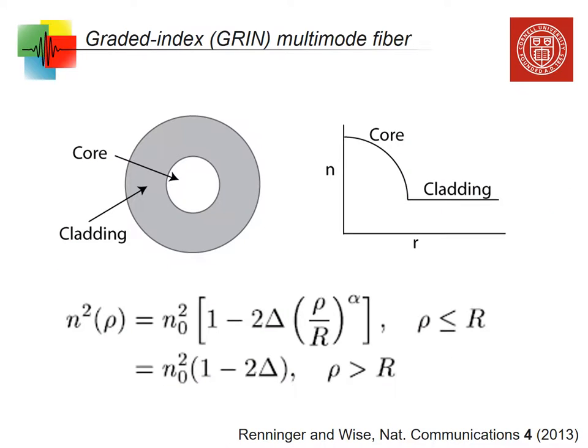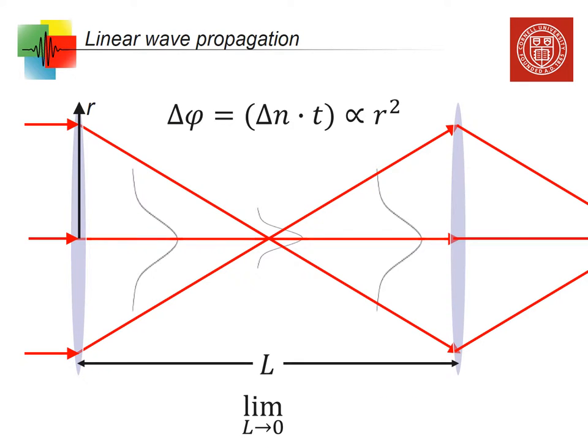So the multimode fiber we're looking at mainly is graded index fiber. It has a parabolic refractive index profile rather than a common step index profile that would look something like this. Just one refractive index here, no continuous variation. The refractive index in the core is larger than the cladding. It's a guiding fiber. You can think about this a little bit like the limit of a whole bunch of lenses, bringing them arbitrarily close together and making them stretched out, you know, for a very long length.